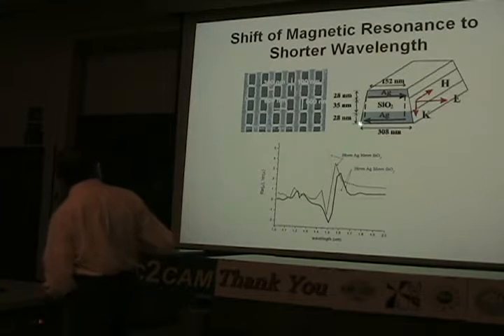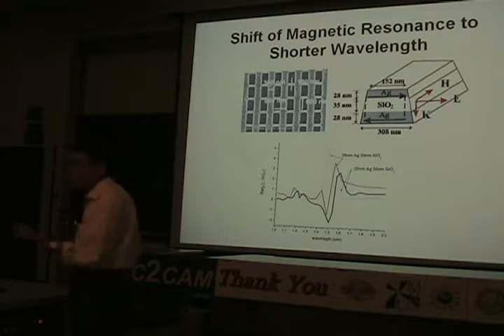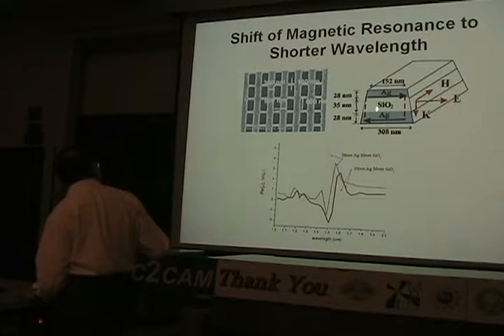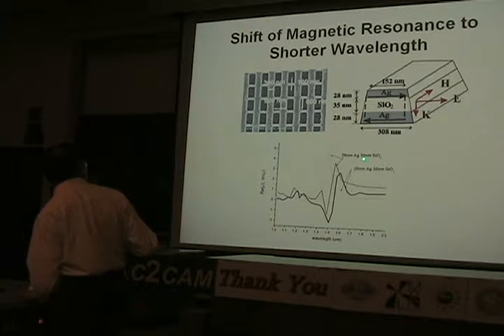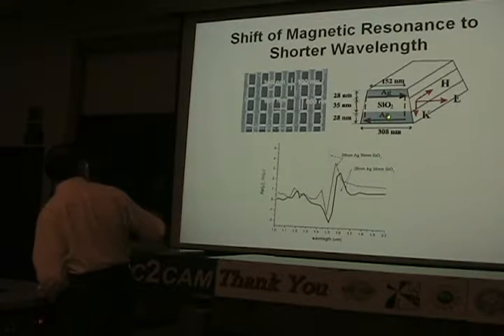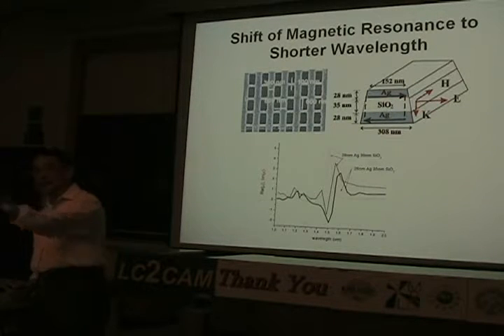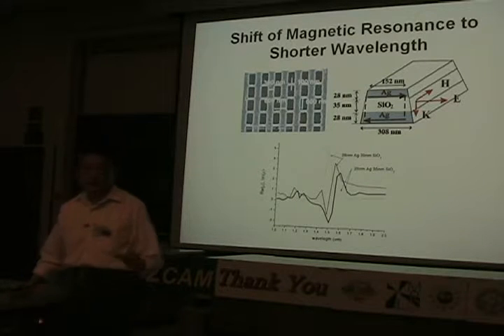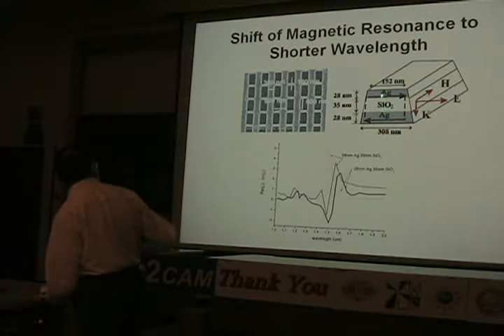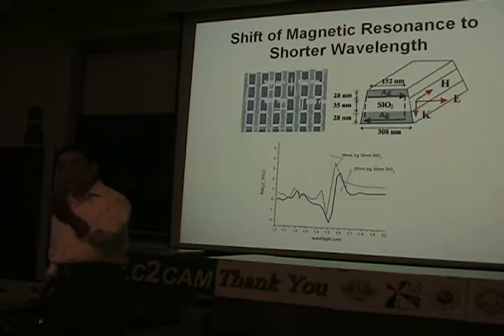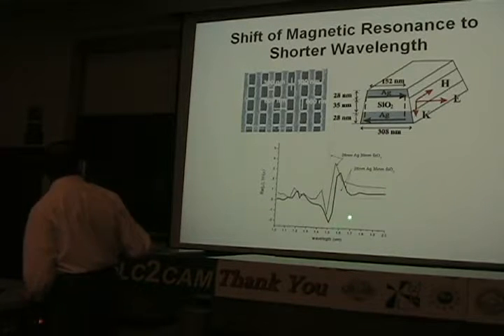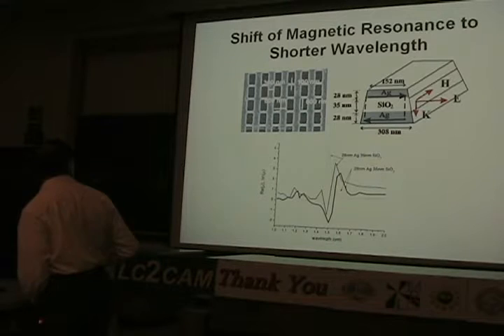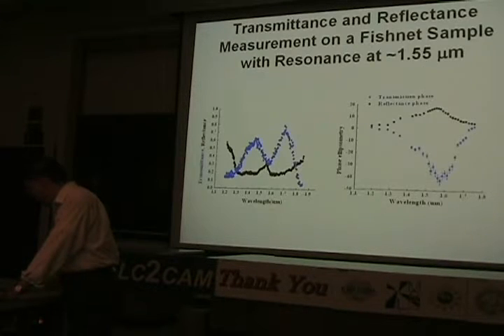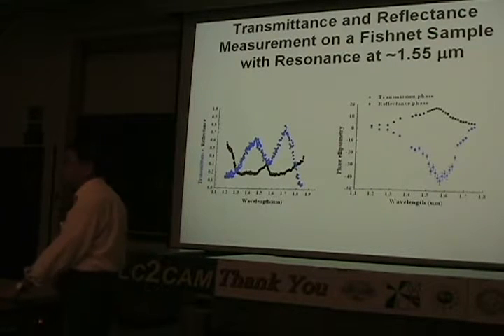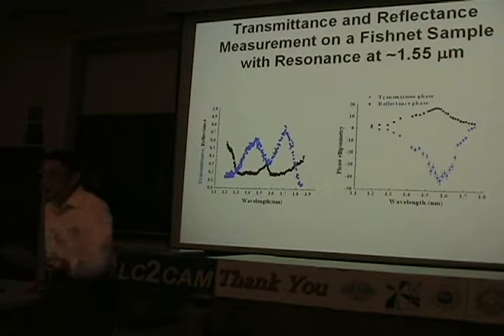So here they just change the parameters, the dimensions, and then here, for example, you have 28 nanometer and 35 nanometer, and obviously for the silicon dioxide, the frequency can change accordingly. So by changing the thickness of the silver or the silicon dioxide, we can actually tune the frequency to 1.55 micron. And here you see one is 1.6 micron, the other is 1.55 micron. And so we now get the material to the frequency we want.